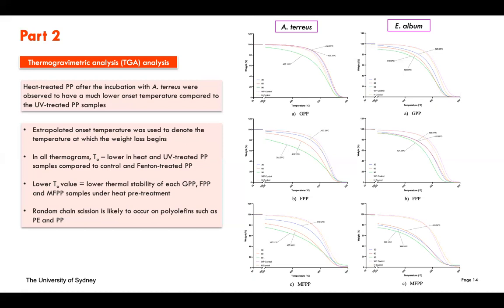I put it in this TGA analyzer, and we heat them from 30 to 900 degrees Celsius. So in between this process, we can see at which temperature this polymer starts to degrade or starts to decline in terms of weight loss, right? So if you can see here in the graph, I've pointed out some of the points.